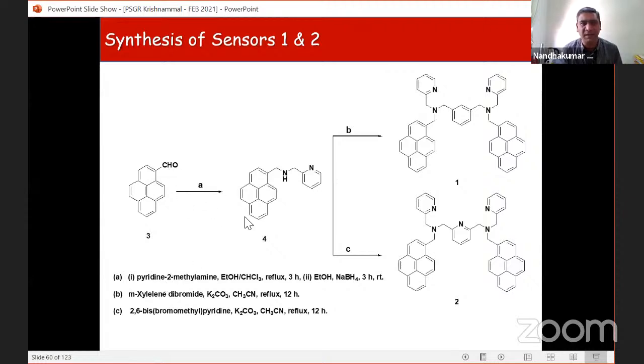So we take pyridine methylamine and then react with the pyrene aldehyde, followed by sodium borohydride reduction. We get this compound, and this is then coupled with 2,6-bis(bromomethyl)pyridine for this one, and meta-xylene dibromide to prepare these. So for these two sensors, the only difference is you have an additional nitrogen heteroatom, but here that is not there.